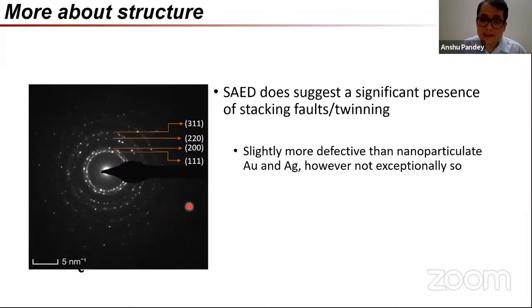If we look at, say, a SAED profile of these materials, we find also that there is indeed a significant presence of stacking faults and twinning. So these are more defective than what a gold or silver nanoparticle might be, but these are not exceptionally more defective. They are about similar, maybe slightly more, but not enough for me to claim that this is a defect mediated effect, perhaps, at least in my mind.